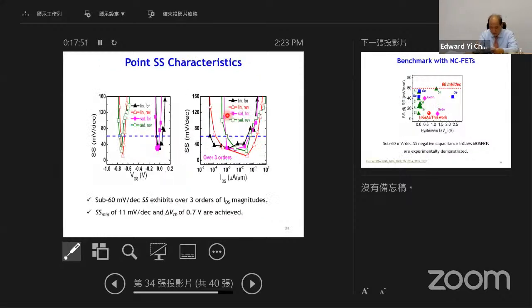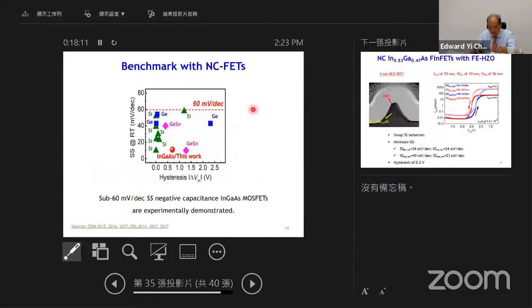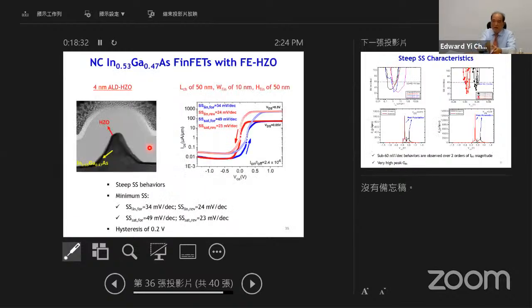Okay. So the next two are the same, which give you the same logic, but we have a MOSFET, and we also have FinFET with this kind of NC material you put in there. You can get very sharp SS, like 10 millivolt per decade. Okay, but of course there's still something to be improved, for example, the hysteresis. Okay, so this is the benchmark of the III-V NC FET, and you can see that the SS is very low. Okay, it's below around 20 millivolt per decade.